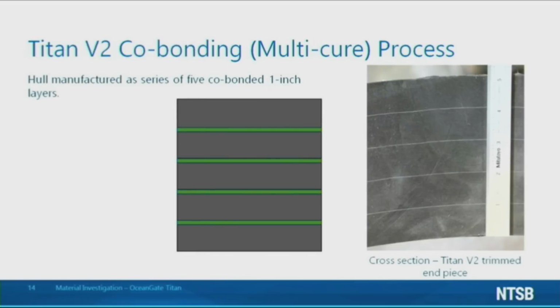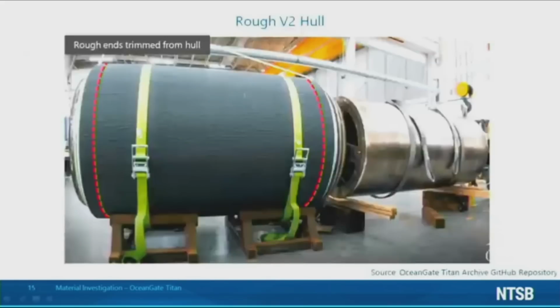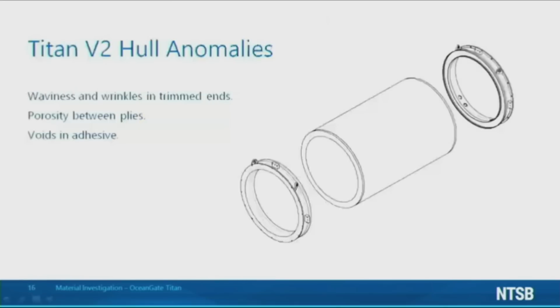The image on the right shows a cross-section through a trimmed end piece of the hull. The lighter lines spaced about 1 inch apart are the layers of film adhesive used to join the carbon fiber composite layers. This image shows the rough V2 hull upon completion. The rough hull was manufactured with excess material at either end, which was subsequently trimmed off.